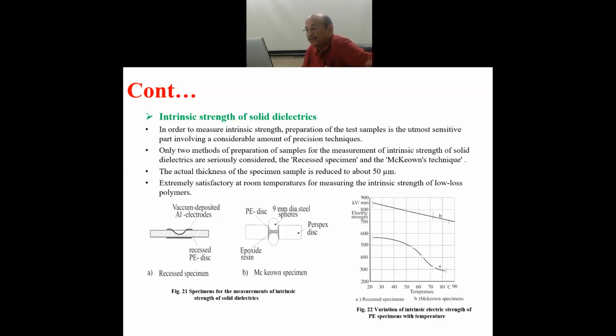For both the types of specimen, the lower one, the recessed specimen, gave a lower value of breakdown strength of the same material, and the upper curve, when measured with McKeown specimen preparation of the sample, gave much higher, to the tune of 850 kV per millimeter. And another thing, the breakdown strength has been measured with increasing temperature.